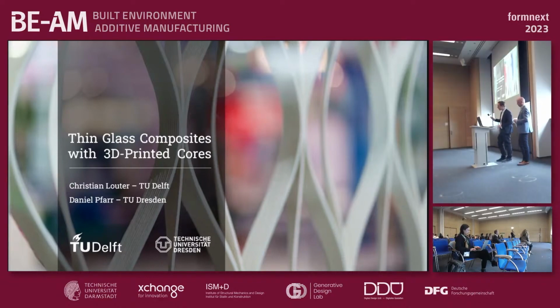Yes, so first we 3D print the core structure, then we take off the 3D printed core, and then we can put it back to apply the adhesive. Then we flip it around to put the adhesive on the other side of the core element, and then we have a core structure with two-sided hot melt, which is cooled down. Then we can stack the glass on it. We put it in a vacuum bag because we want to achieve the curvature as well, so it is pressed down to the adhesive, and then it goes into an oven at 120 degrees, for example. And then the hot melt is melting, and it's reconnecting, and then it's connecting the core structure with the glass. So it's a second step after the printing.